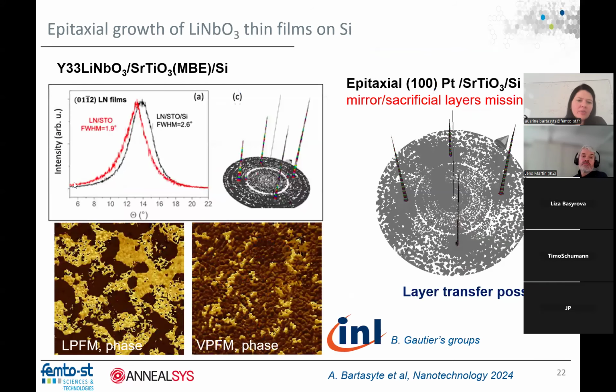So we optimized this, and then we checked we had very similar quality if we would grow lithium niobate directly on the strontium titanate. The rocking curves were relatively large, but because the film has a tilt from the substrate, the film in that case is not Y33, it's Y36, because the film is tilted from the substrate plane by 3 degrees. But to go further, we needed to grow the electrode, Bragg mirror epitaxially, sacrificial layers, and so on. It was quite a lot of work. We grew platinum 100 epitaxial on this template, but it was complicated to make the complete structure for BAW devices.